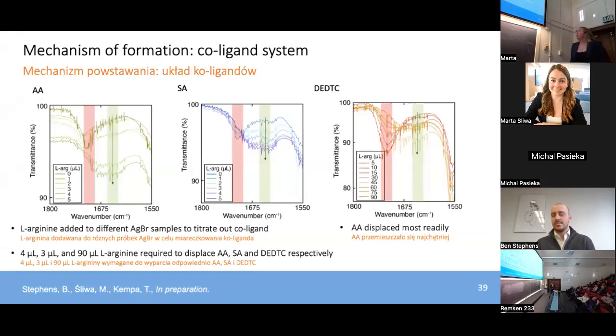We also see that the L-arginine doesn't as effectively kick off the carbamate. It takes roughly 15 to 20 times higher volumes to kick off the carbamate ligand, and this is likely due to some of the functional groups that the carbamate uses to associate with the silver bromide, making them more strongly associated to that silver bromide nanoparticle surface and harder to kick off.